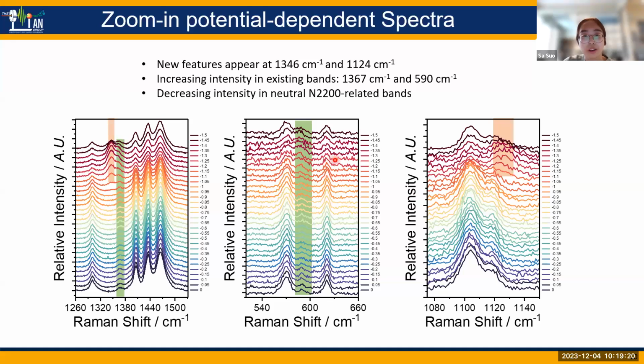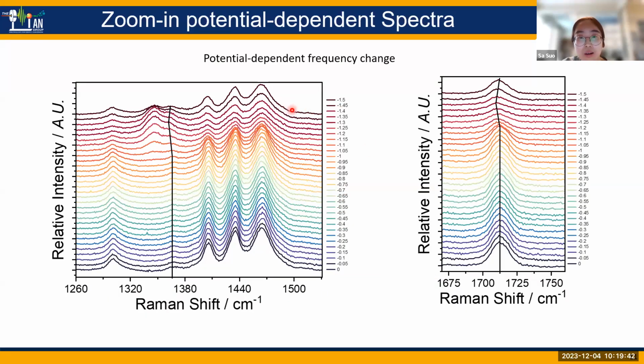So this is what we observed in terms of Raman amplitude or intensity. And meanwhile, we can also see the neutral N2200 related peak has a decrease. We will see this trend clearly in a bit. We can also see a frequency change in the Raman spectra upon polaron formation. For example, the carbonyl bond over here shows a constant frequency, and then after the first reduction happens, there is a redshift of the frequency, and then a recovery after that.